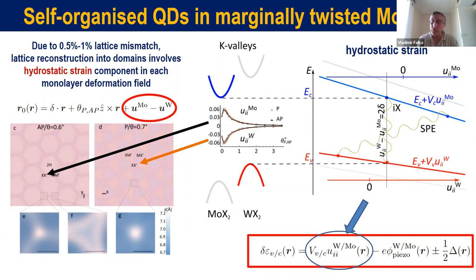And when we combine together all the factors that we established before, the effect of piezoelectric potential, and also the interlayer charge transfer of electric type, which also produce the interlayer energy shifts, we checked that for a small range of misalignment angles between 0 and 1 degree, the effect of hydrostatic strain is numerically, quantitatively the strongest, and this determines a different physics of those heterobilayers as compared to twisted, marginally twisted homobilayers.